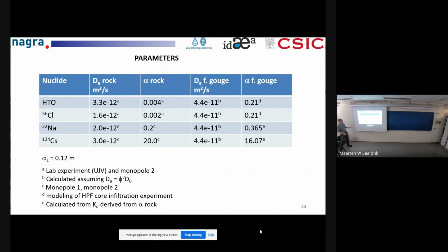Yes. These are parameters I use for the microscopic calculations, based on results of the tritium. These are diffusion coefficients in the rock: tritium, chloride, sodium, and cesium. It's not exactly the values I just showed because this is based on previous results, but they are similar values. So it's translated into capacities, and then we have fault gouge, because these individual fractures are filled with fault gouge.